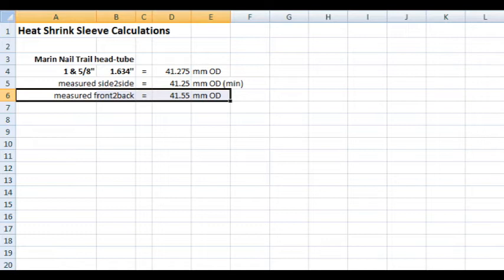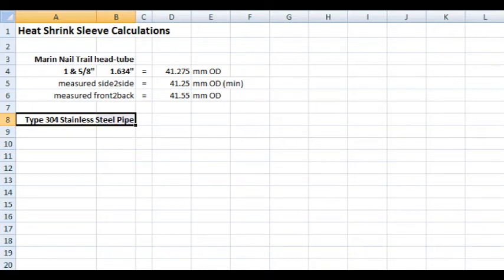So I've got to find the right type of steel to make it out of. If I make it out of mild steel, that's no good, it's too soft. I'd like to make it out of carbon steel, but I can't, because when I heat it up to dull cherry red, it's going to anneal it and it's going to lose all of its strength. And the only thing that keeps its strength when it's hot is stainless steel. There are various grades of stainless steel, but the only one I could easily find available was type 304.